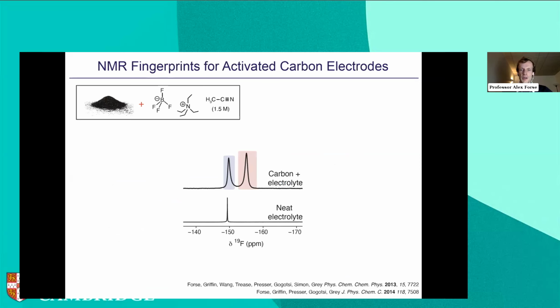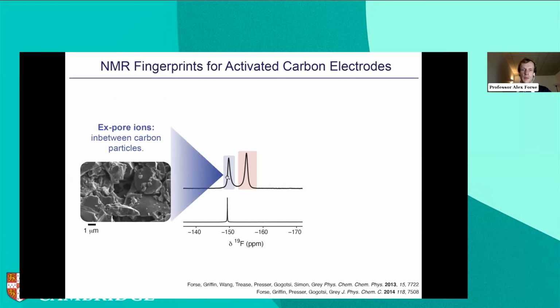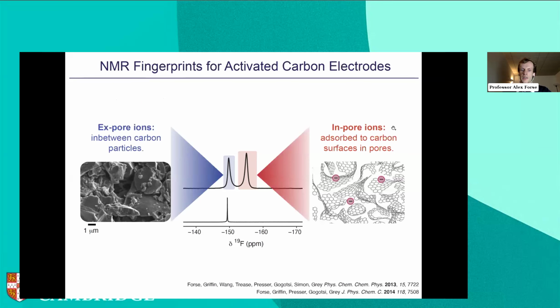So just to introduce you to these NMR fingerprints for supercapacitors, these are the kinds of things we see here. So again, it's a carbon electrode material soaked with the liquid electrolyte. And when we've got the carbon and the electrolyte together, what we see is 2 peaks in our fingerprint. Whereas when the carbon's not there, and we've just got our electrolyte, we only see 1 peak. So what's going on here? Well, this left-hand peak is coming from free liquid, sort of sloshing around in between the particles of our electrode. But this right-hand peak, on the other hand, is more interesting. And this is coming from our ions that have gone into the pores of the carbon electrode. And so the ones we'd expect to be involved in energy storage.